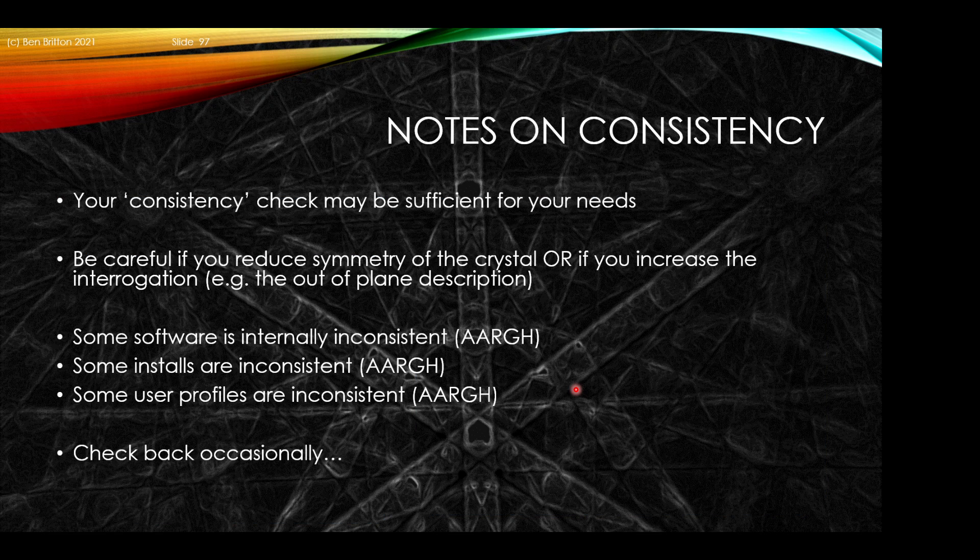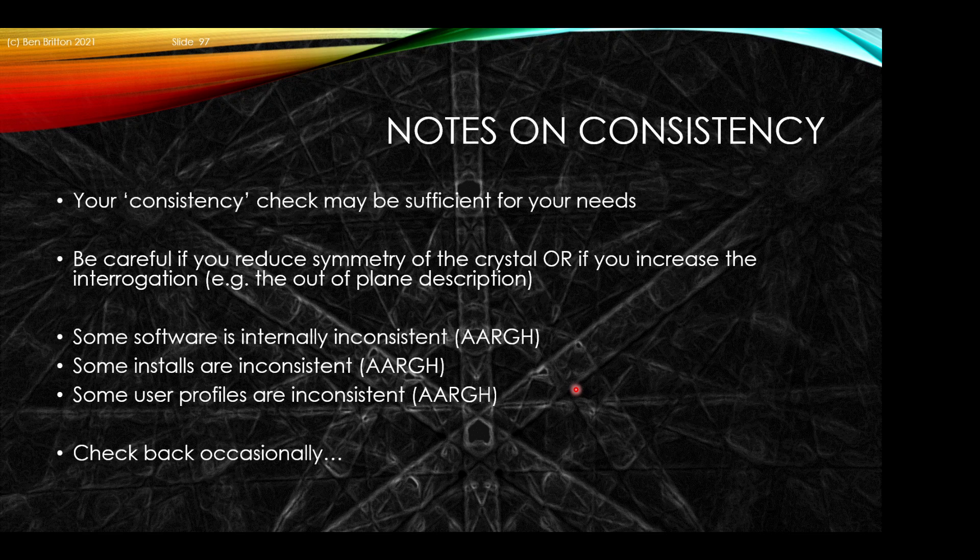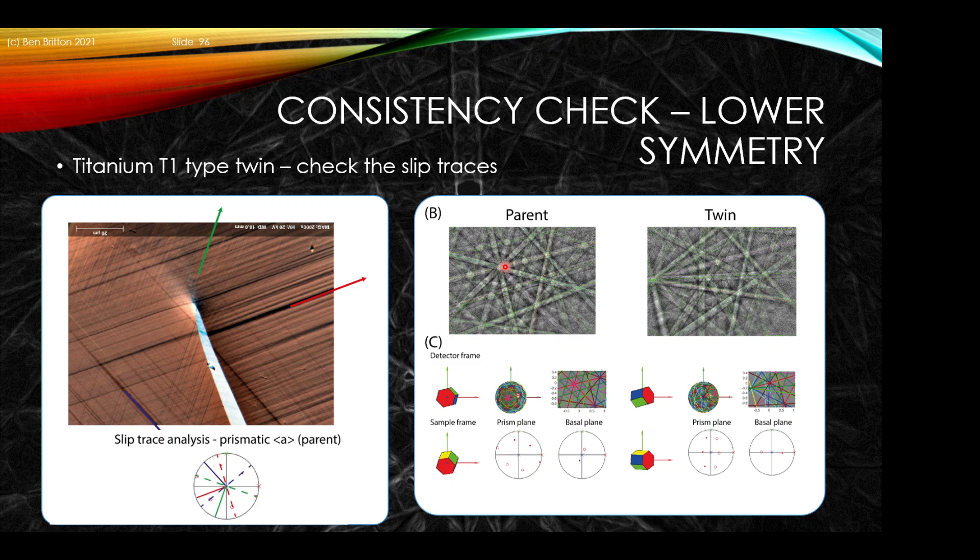A note on consistency. Often it's much easier to check consistency rather than whether something is absolutely correct. The consistency for your material system may be sufficient, but please be careful if you reduce the symmetry of your crystal or increase the interrogation you're interested in. For instance, you're not just looking at the surface plane traces, but at the subsurface inclination of the boundaries. That's where the 180 degree problem can cause you issues. Some software is internally inconsistent, which frustrates me immensely. We've told people, we've got some stuff fixed. Some installs between microscopes are inconsistent. And some users may uncheck boxes that can change and create inconsistencies. So do check back occasionally and see whether you can simulate a diffraction pattern or the bands for your diffraction pattern given all those settings. You can see how the math follows whether you understand the conventions present in this problem.